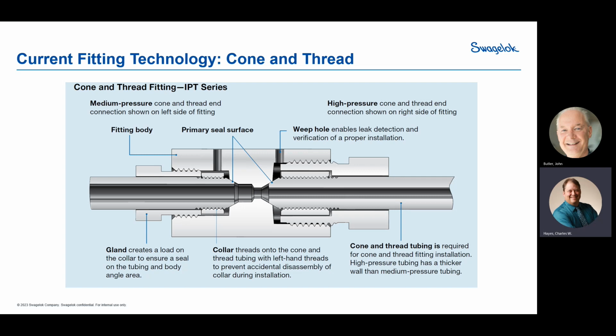The other problem is the cones themselves are often machined in a shop, in the field, and they really depend on the skill of the operator making them. They're not done on large rigid machines in a factory with high quality control with precision surface finishes. So chatter, which is vertical lines running along the axis of the part along the sealing surface, leads to problems with continuous pore structures, as do groove marks due to bad tooling and not enough lubrication. And of course, for the lubrication they're sitting there with a little bottle squirting oil onto it, so there's no consistency in how that's done. A lot of inconsistency on that primary sealing surface causes a significant number of problems.